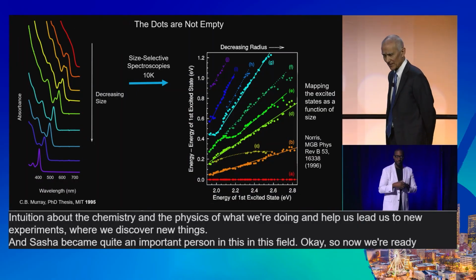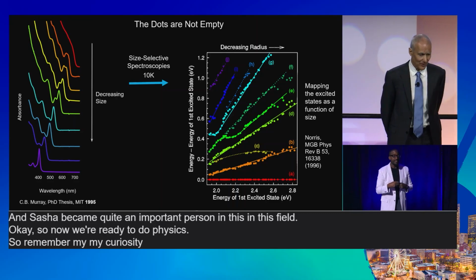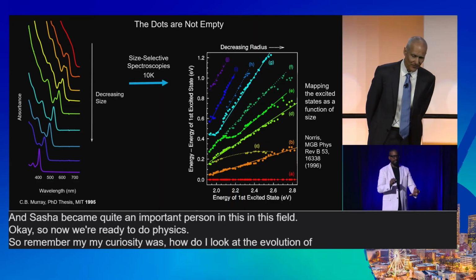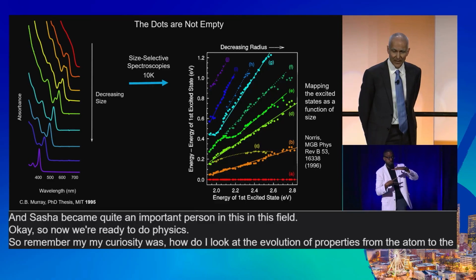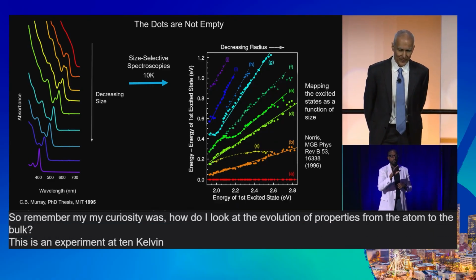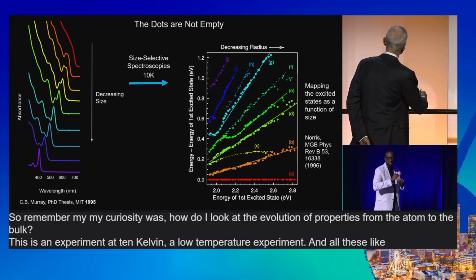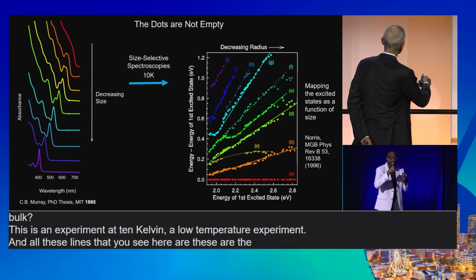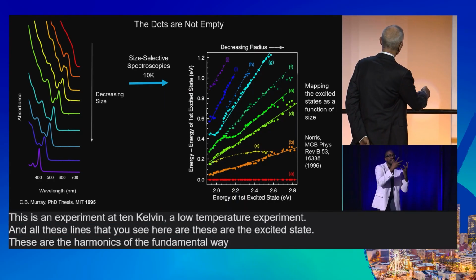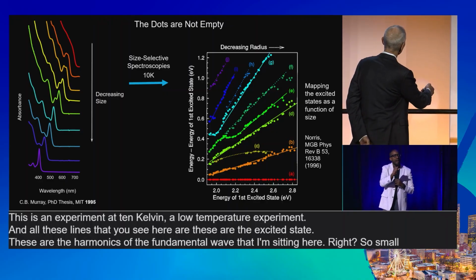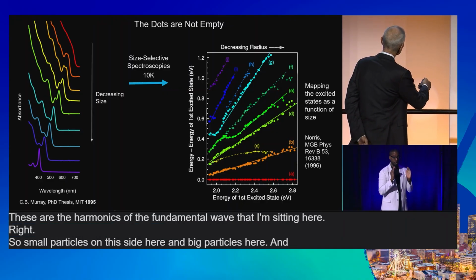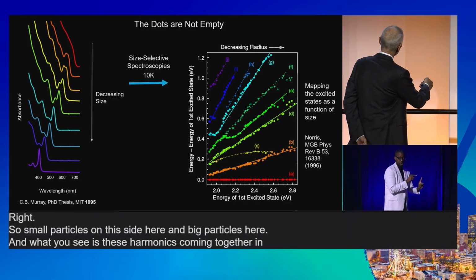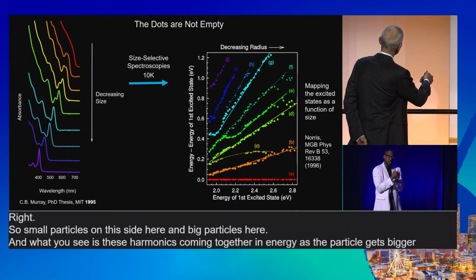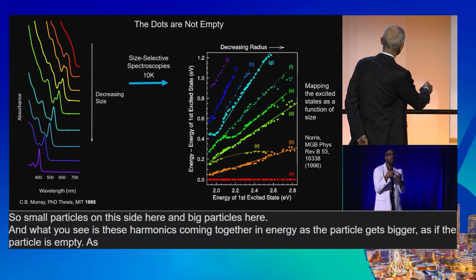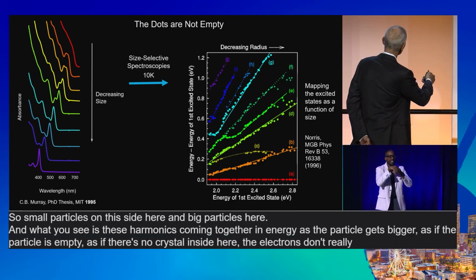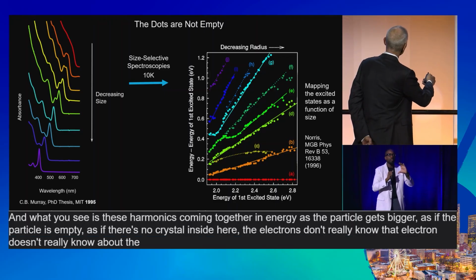Okay, so now we're ready to do physics. So remember, my curiosity was, how do I look at the evolution of properties from the atom to the bulk? This is an experiment at 10 Kelvin, a low temperature experiment, and all these lines that you see here are the excited states. These are the harmonics of the fundamental wave that I'm sitting here, right? So small particle is on this side here, and big particles here. And what you see is these harmonics coming together in energy as the particle gets bigger, as if the particle is empty, as if there's no crystal inside here. The electron doesn't really know about the crystal that's inside the box.